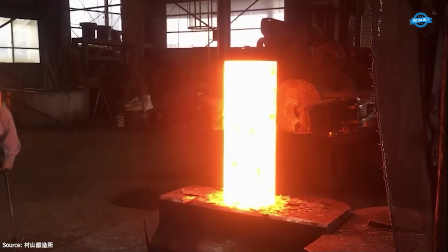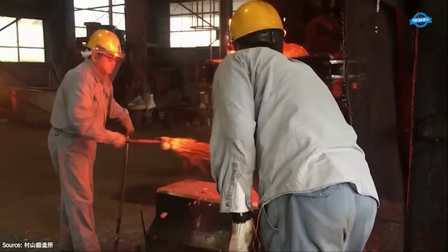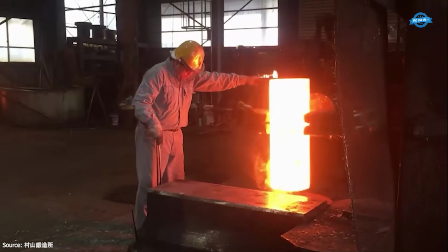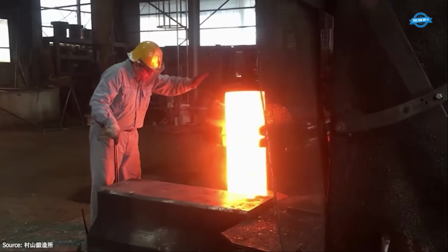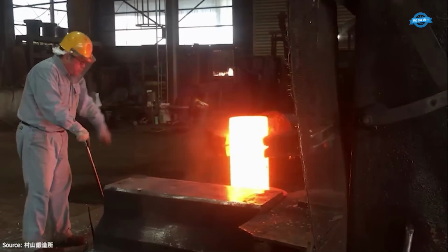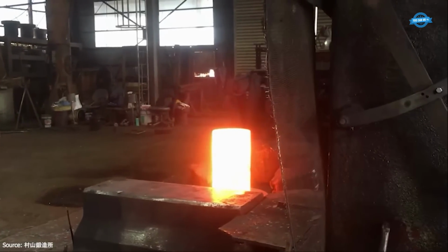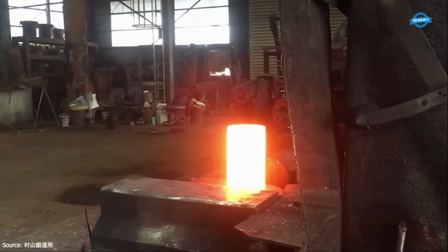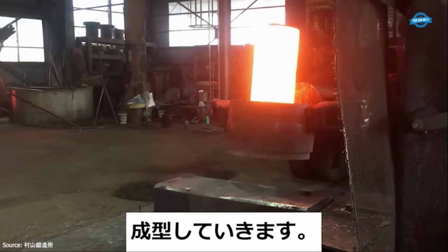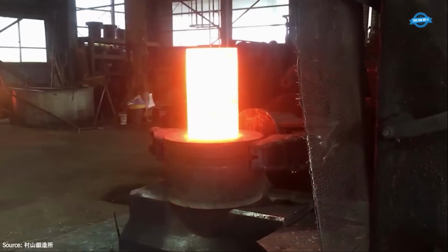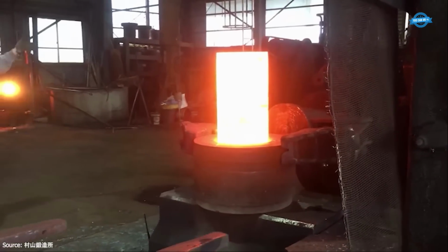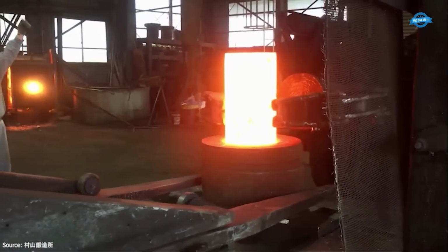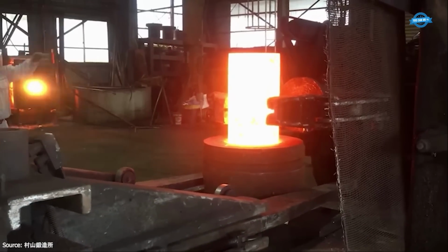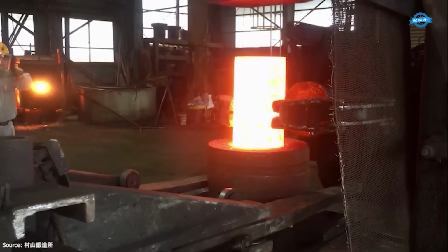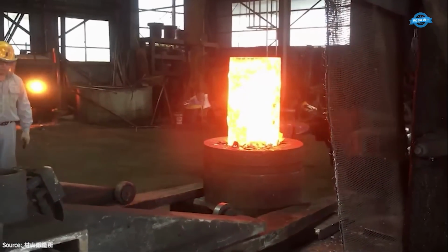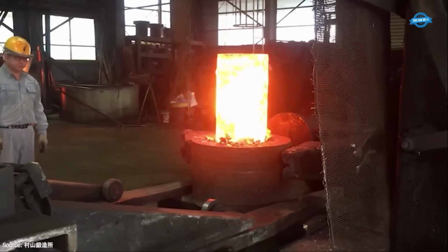The process begins with material preparation. Large billets of S45C medium carbon steel, known for its excellent strength and machinability, are selected. Each billet is cut to a specific dimension based on the final size of the coupling to be produced. S45C is typically standardized to have a carbon content of approximately 0.42% to 0.48% and tensile strengths ranging from 570 to 700 megapascals after heat treatment.